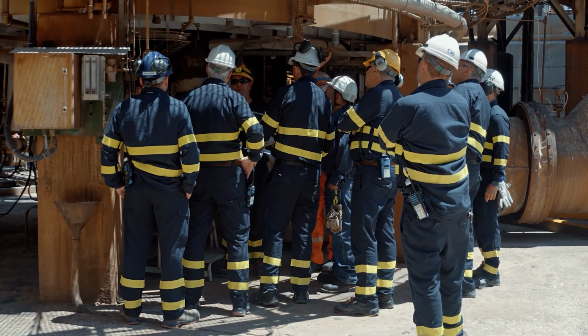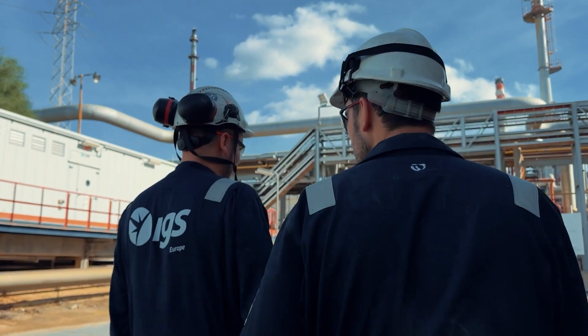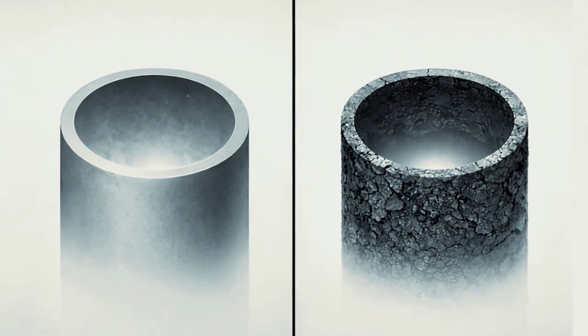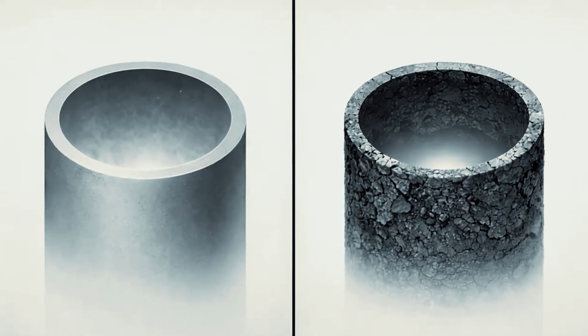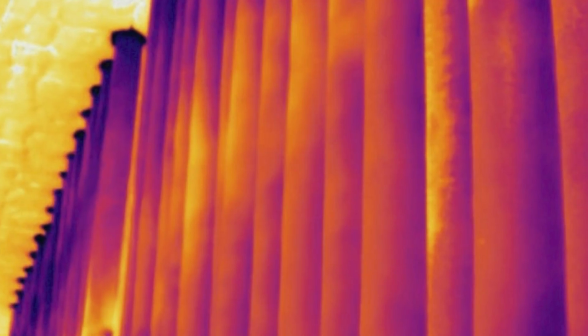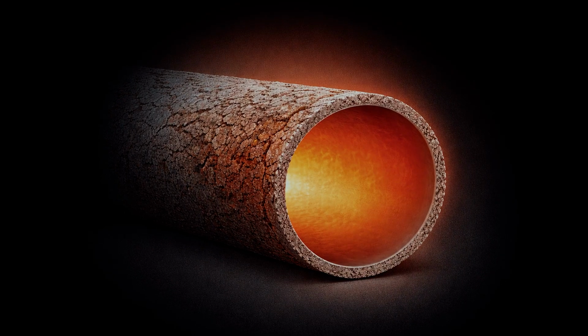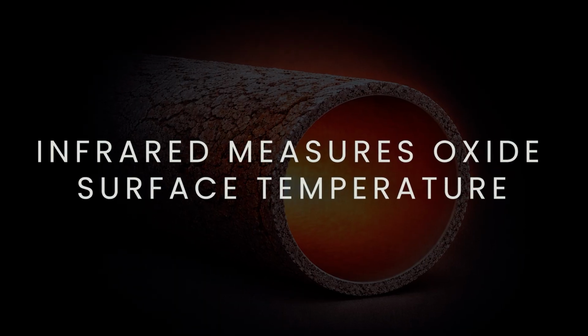Our crews at IGS have removed this type of scale from hundreds of fired heaters in the last 20 years across a wide range of process units. There's a difference between the measured surface temperature and the actual tube metal temperature when we do our infrared inspections. This is a common topic that we have discussed with customers. Infrared thermography measures the temperature of the oxide layer on the surface. It's not measuring the steel beneath it.